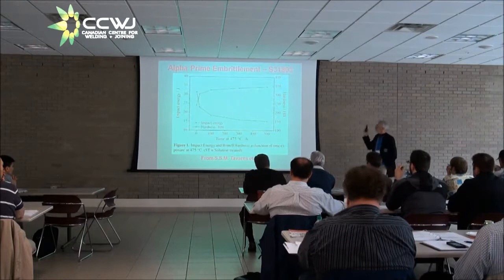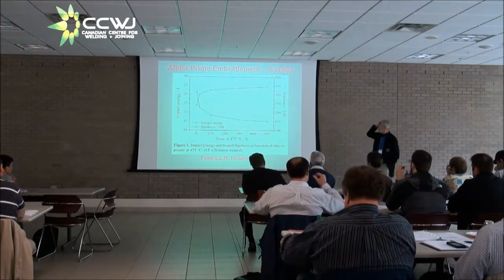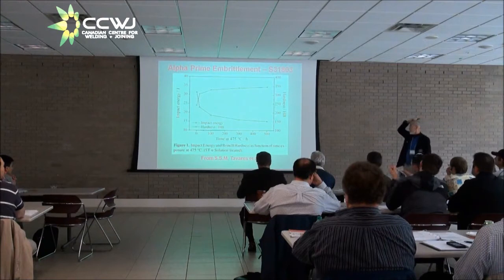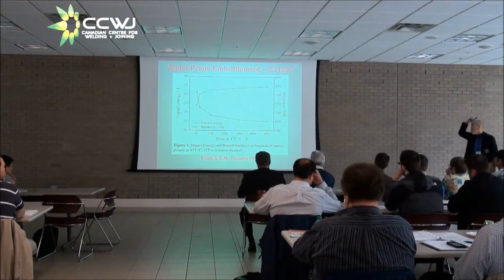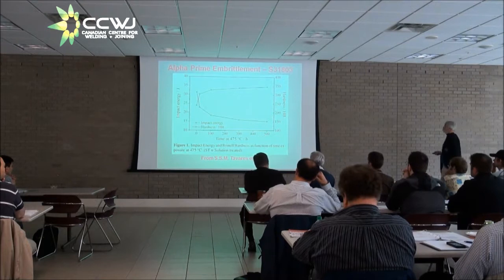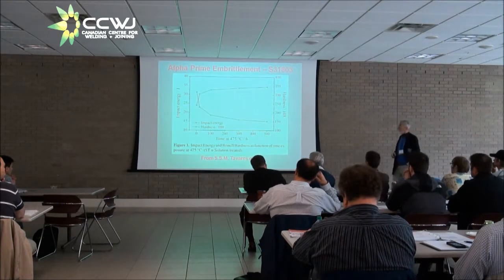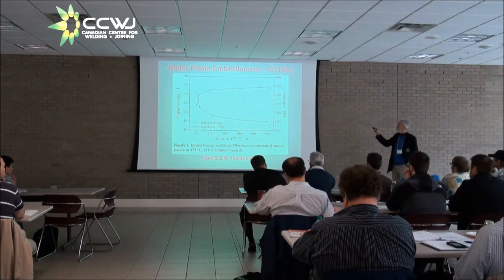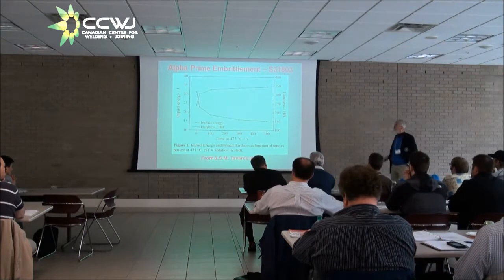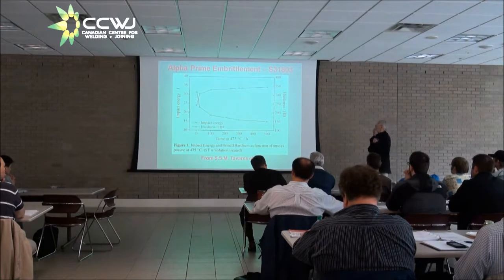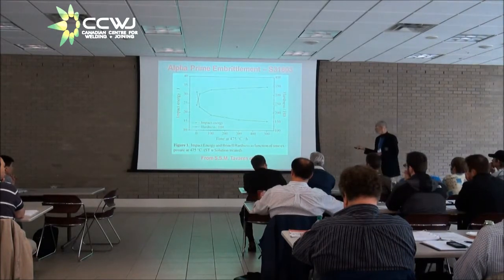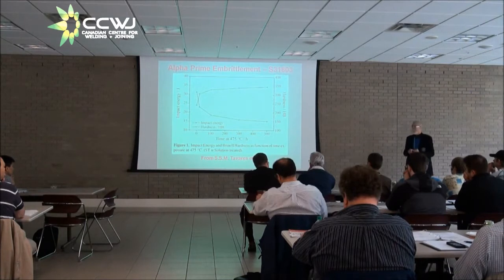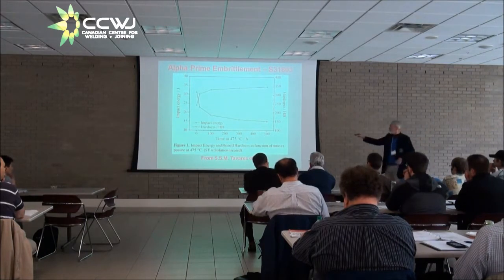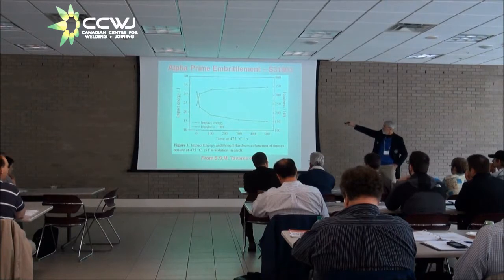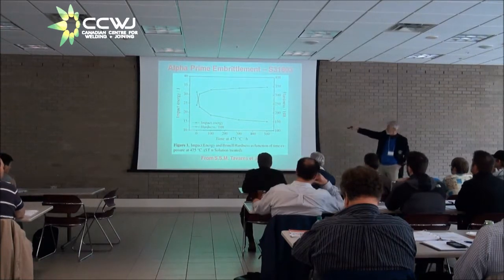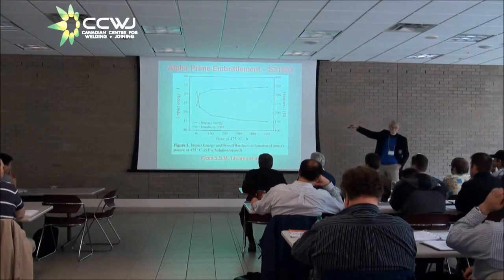A guy named Tavares published a paper on the internet from which I borrowed this material. What he's looking at here is thin wall pipe, so the Charpy impact value shouldn't alarm you too much. But what he's looking at here is the mechanical properties of 2205 material using the old S31803 number, so I'm not sure exactly what the nitrogen number is. But he's looking at time at 475 degrees C on the horizontal axis. And then on the vertical axis, on one side we're looking at impact energy in joules. And these are very subsized Charpy specimens because it was thin wall material.